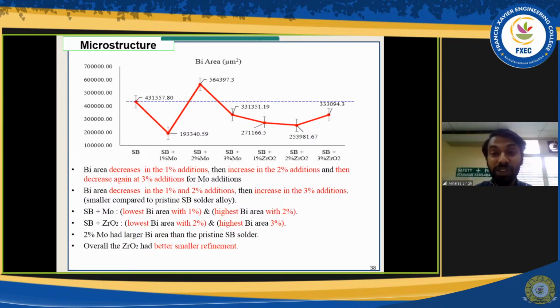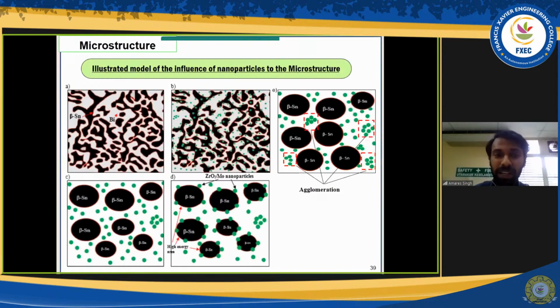But we can see that the zirconia here had a lower Bi area. This is simply because of the small size of the zirconia nanoparticles. This is again a model that I've developed. In picture E, this is not the SEM image; I've extracted and drawn this model from the SEM image, so I know what happened at the particular sites of the Bi and also Sn. I've labeled here the Sn as the dark area and the Bi as the white area.